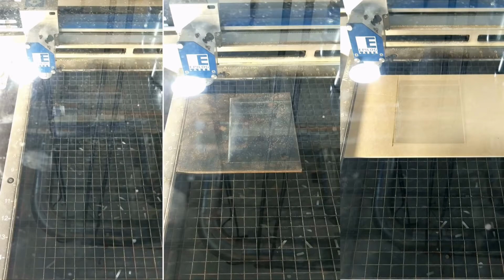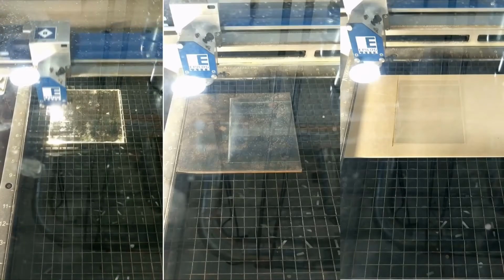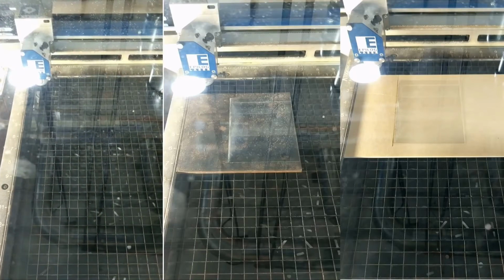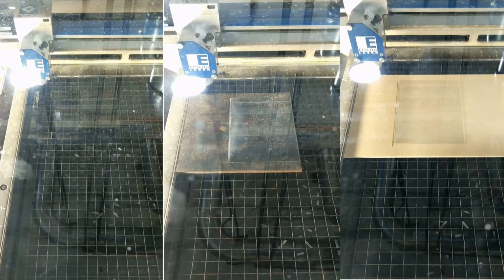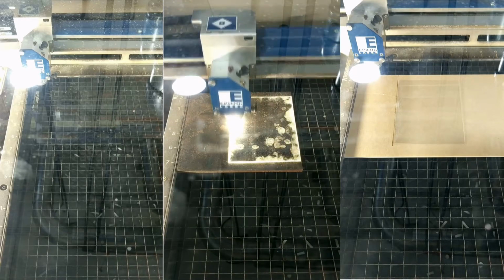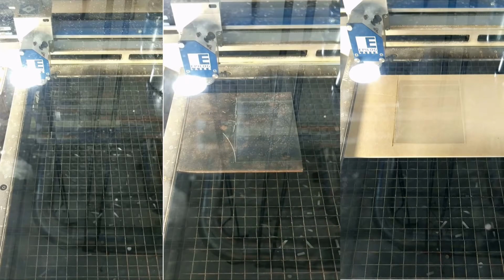Next, back to what I was initially talking to you about, we played with the laser cutter available at the Boston Build Space, playing with parameters of the laser cutter, namely the intensity of the laser, the speed as well, and different backing materials. And this is what you're looking at right now. So no backing was not extremely satisfactory. The edge condition was just not very good. The steel backing was not satisfactory either. You see how the edge condition is really bad.